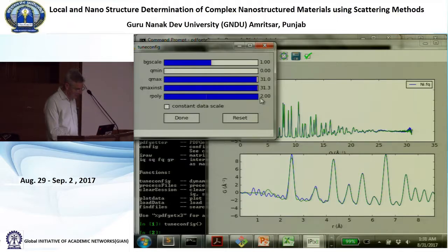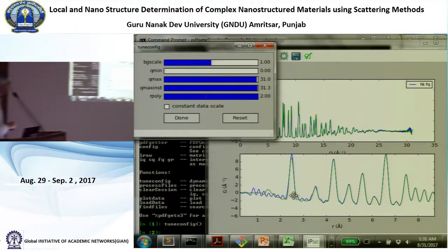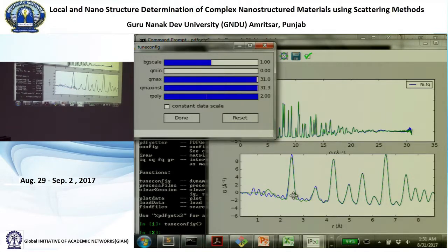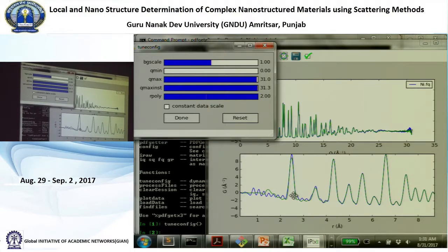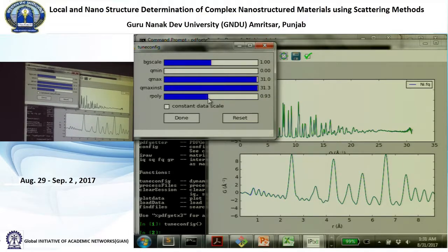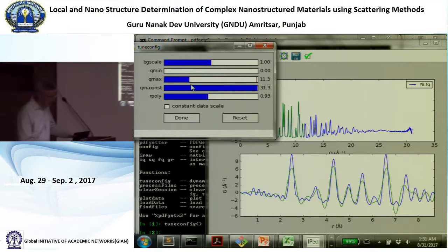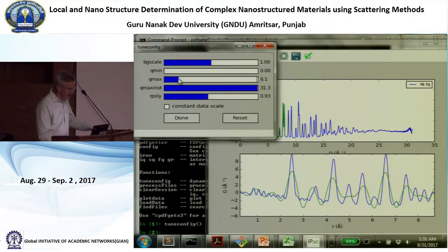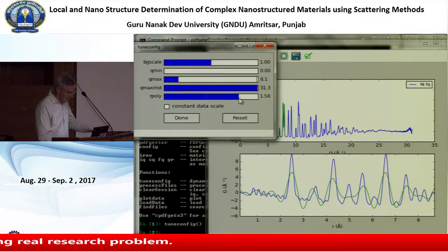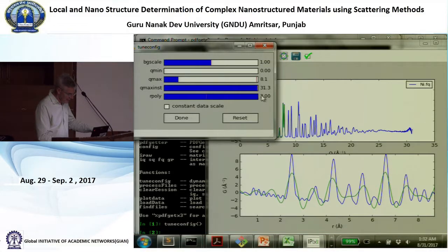And we can take it up to 2 here, and now it's basically going very flat here, and then you're getting this ripple there. So this parameter is actually important if you have a low Qmax, because you can really overdo things. So what we can do is we'll move this back to 0.9. We'll move Qmax down to, let's say, 8. And now we'll increase this Rpoly. Okay, even then it's too much.